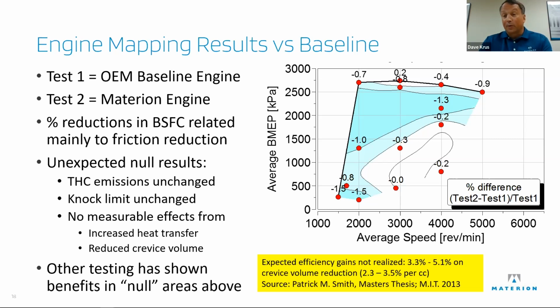We couldn't see it. We actually ran for a short period of time some performance rings in there as well, the higher conductivity piston rings. That's in the white paper, you could read it. It didn't show any effect on knock mitigation at all. But from what we heard from other testing, those rings can have an effect on knocking by cooling the crown. So other testing, as I say, has shown benefits in those areas.